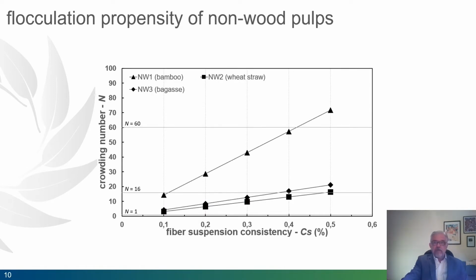Now we see the flocculation propensity for non-wood pulps that shows a performance equivalence between the bamboo pulp and the softwood pulp. The results for pulp made from wheat straw and bagasse are closer to hardwood pulps, meaning that these non-wood pulps are less sensitive to flocculation. This can be explained by similarity between trends in fiber length and length to coarseness ratio.